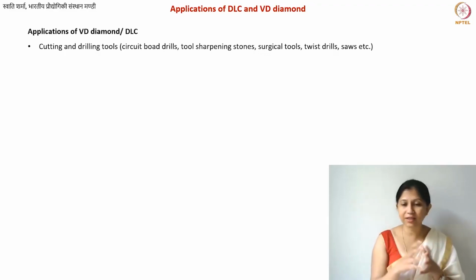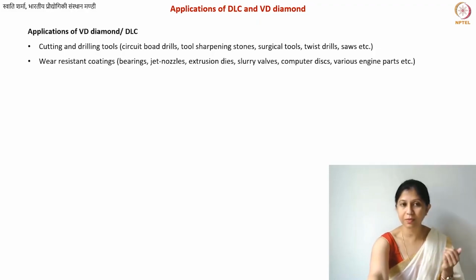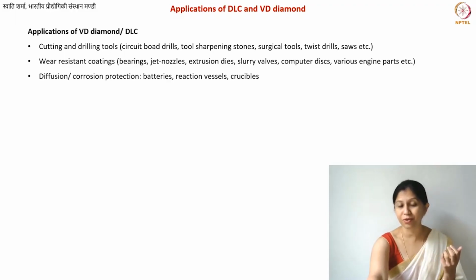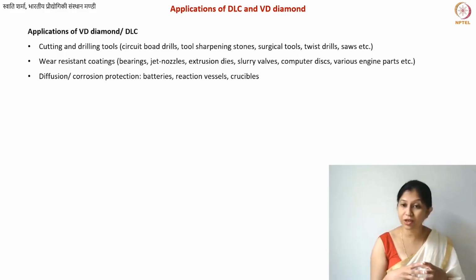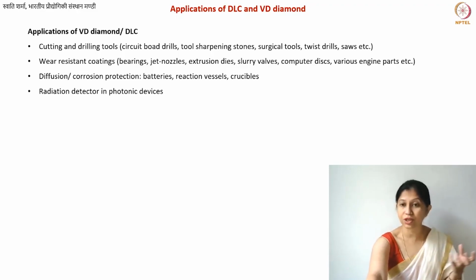You actually have these kinds of coatings also on various surgical tools, because these are chemically very inert coatings. Whenever you need an inert coating and you want to protect your tool from thermal as well as mechanical wear, you can use vapor deposited diamond or DLC. Again, on various bearings, even jet nozzles and extrusion dies, all of these parts wherever you want wear protection. You can also use these coatings for corrosion protection, for example in batteries, especially sodium batteries, and as lining in reaction vessels and on crucibles, for protecting from corrosion and diffusion. So it can also act as a diffusion barrier.